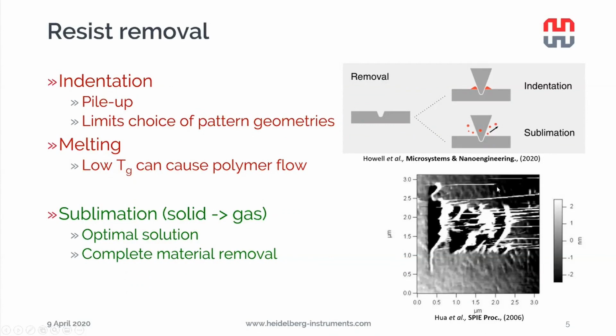Therefore, in our opinion, the best thing that we can do is sublimation. We indent with the hot tip, and everything that gets in contact with the hot tip gets directly changed into the gas phase. So we don't have any residues, as it's completely removed. We don't have any pileup on the sides of the pattern, and we get a nice clean indentation or hole where the tip has indented and no more material around it.